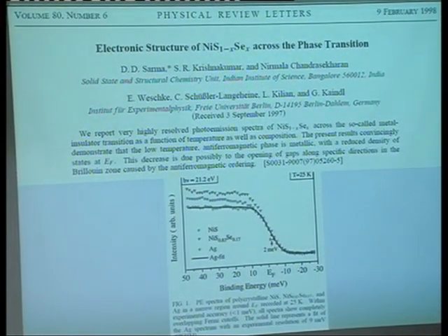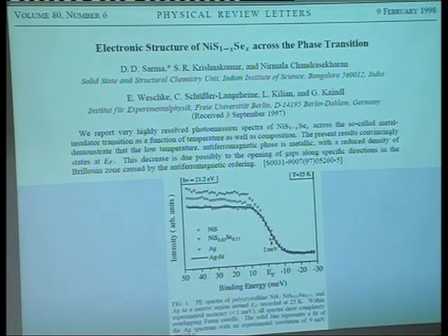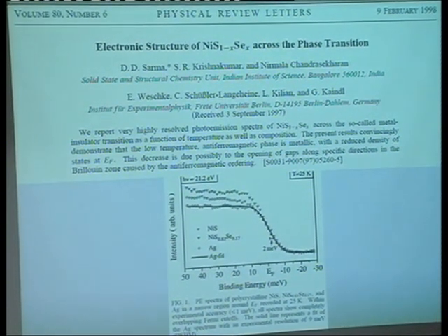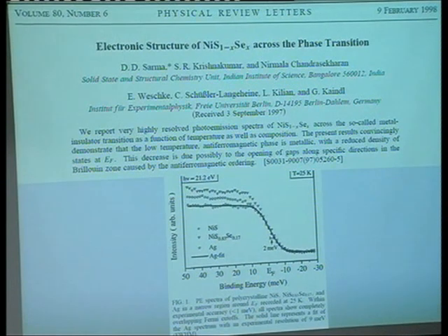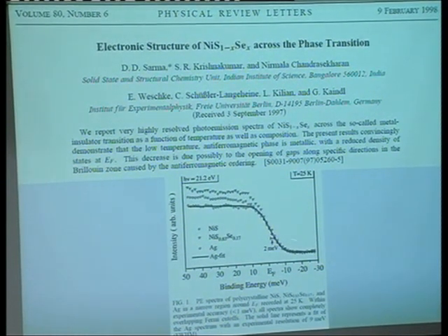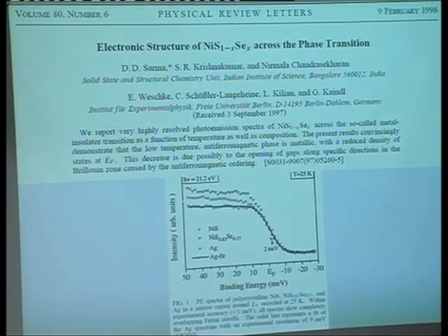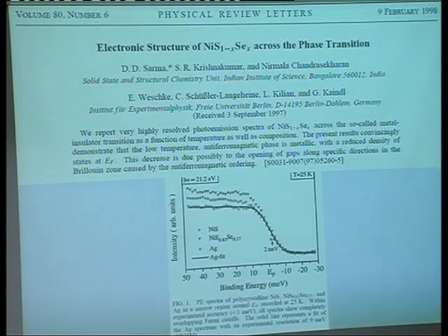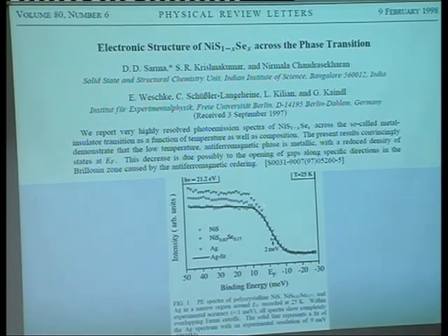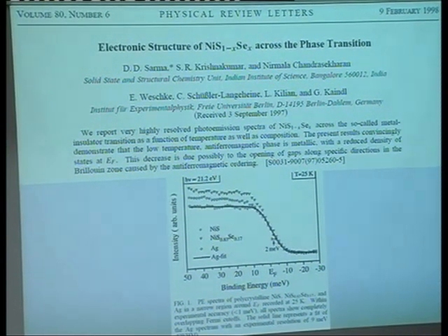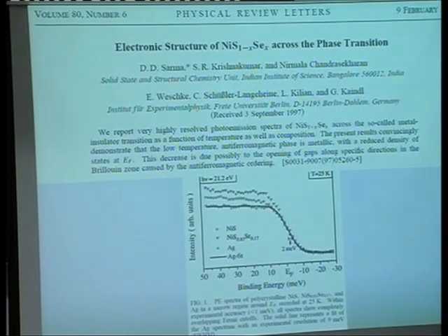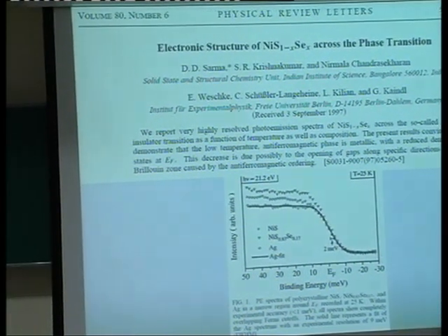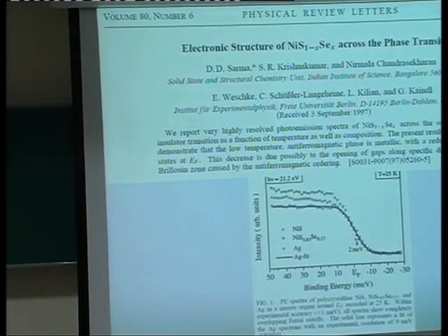And there's a 2 meV bar drawn for you to tell you that we can resolve everything down to about 1 meV or so. The data we have, this is a silver data, which has a solid line through it. This is the nickel sulfide data, and this is the nickel sulfide doped with selenium in such a way that it's totally a metal at lowest temperature. And all of them completely coincide over here with the Fermi energy.